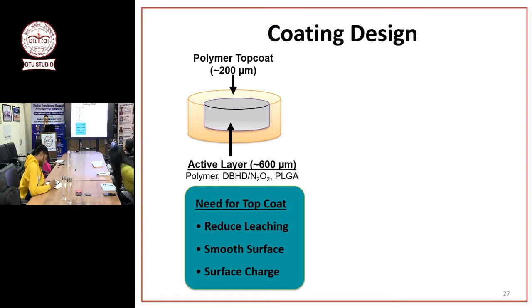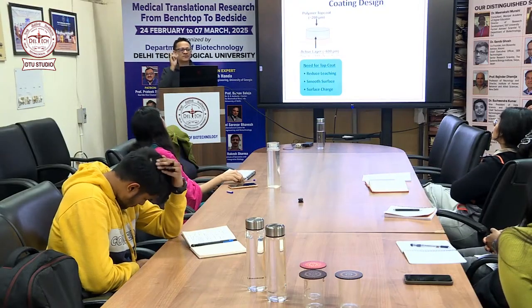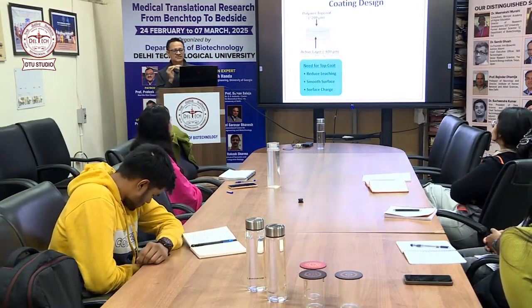What else? This is what we did, right? This is why it took us so much time. Thickness of the coating. But also remember, in the real life catheter example, we cannot play too much with the thickness, right? Because we need to have a certain inner diameter, we need to have a certain outer diameter, and we have very little room to play with the thickness. But you are right. Can we make the active layer very thick, top layer very thin? Compared to each other, how much can we play? So let's say, I'm just saying as an example, 800 micron is my total thickness allowed. Should it be 400, 400, 200, 600, 600, 200? So we played with that a lot. Okay.